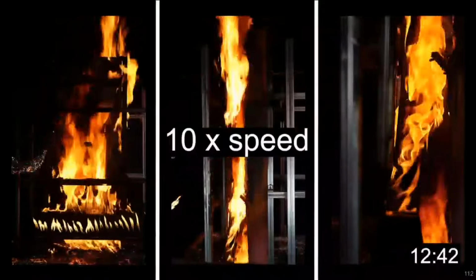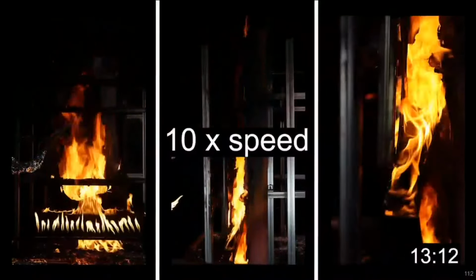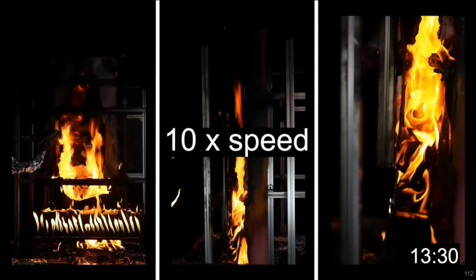This continues until about 13 minutes and 30 seconds, and after this point, we will be looking essentially directly at the K15 insulation through the Reynobond PE, or where the Reynobond PE used to be. The last visually obvious flaming from the polyethylene from the ACM occurs at around 18 minutes when I let this run. The Kingspan K15 continues to smolder and flame until the experiment is terminated after about 20 minutes.